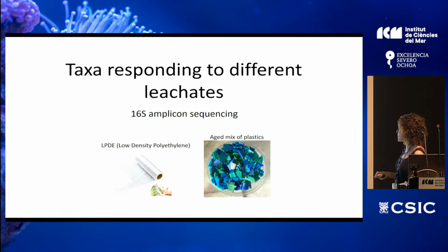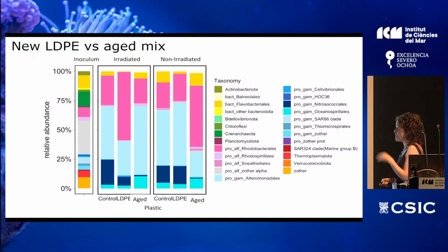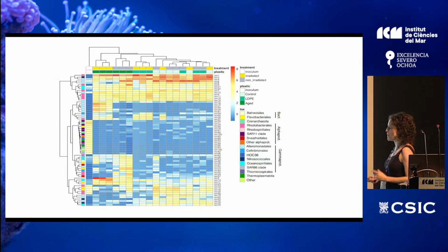So, and this is, we use LDPE, new LDPE, and aged plastic. These results are not published yet, but I show you just to show a little bit that there are some differences. Here, even if it seems that the community composition is pretty homogeneous, when we look at the abundance of each taxa, we can see some differences.